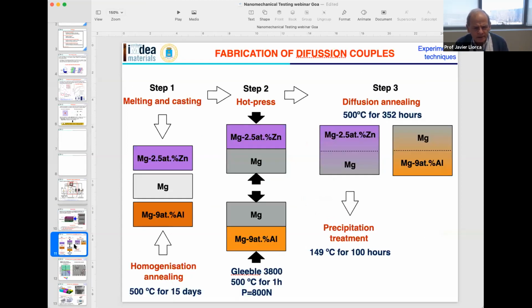So the first part in this investigation is the fabrication of the diffusion couples. You have a slab of magnesium, then you have a slab of a master alloy, in this case magnesium with 9 atomic percent aluminum. You have another slab of magnesium with 2.5 atomic percent zinc. You just put them together and do a homogenization annealing treatment that may take 500 degrees for 15 days. Of course, if you let it enough time, there is some diffusion there.